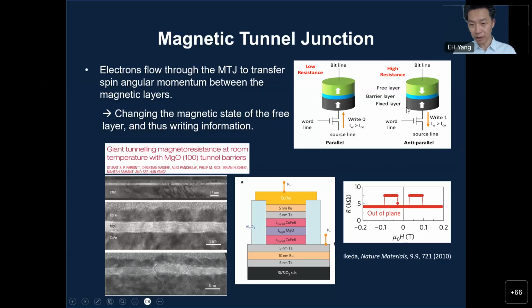So on the right top, it shows the structure here. So basically, the structure consists of 3 layers. One is free, barrier, and the fixed layer. Okay, so fixed layer is a little harder magnet. Free layer is a soft magnet, so you can flip the magnetic state easier. And the barrier layer basically is a barrier. You can use some dielectric materials there. Okay, that is dielectric on the left here. Dielectric material here is magnesium oxide. Another work is published in Nature Materials in 2010. Also shows this very complex structure and shows this magnetic